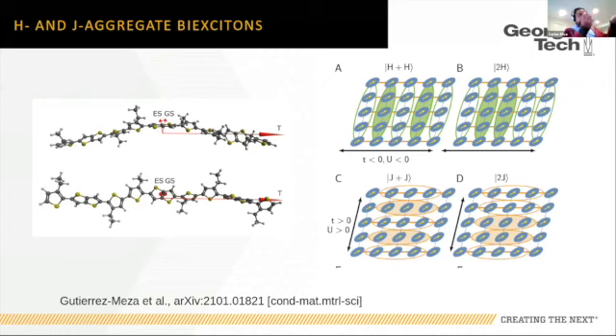If we now decompose this 2D spectrum into the real and the imaginary part, absorptive and dispersive part, we see that 0-0 inverts its character: 0-0 looks absorptive at zero time, but becomes dispersive. 0-1 looks dispersive, but becomes absorptive on a time scale of 100 femtoseconds or something like that, which is roughly the dephasing dynamics of like 50, 60 femtoseconds. So the dephasing is definitely very sensitive to the fact that it's an aggregate, and the details of the aggregate are